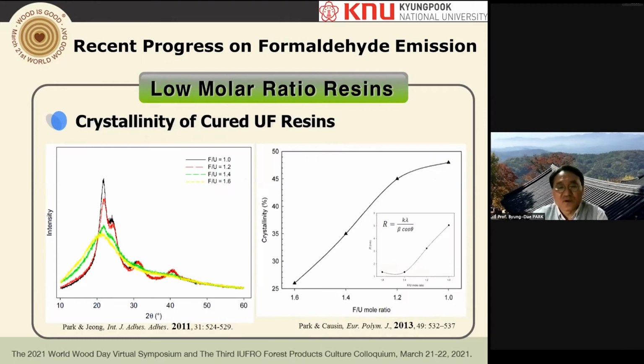And then we question why, and then we look at the XRD, X-ray diffraction. As you see here, the low molar ratio resin 1.0, 1.2 is much more crystallized compared to higher molar ratios, which are amorphous. And then we calculate the crystallinity of these resins depending on the molar ratio. About 1.0 molar ratio has about 48% crystallinity. That means almost half of them is crystallized, the other half is amorphous. And also the crystal size increases when you have low molar ratio resins.